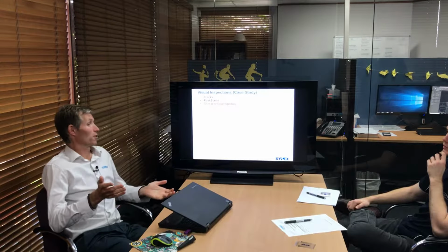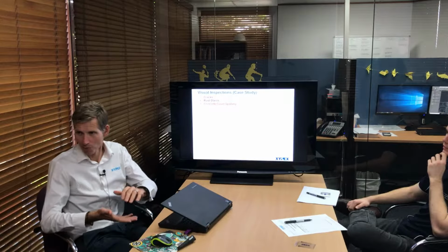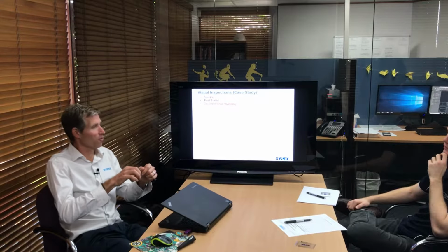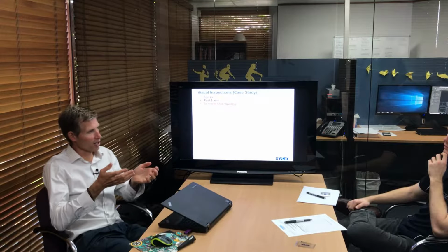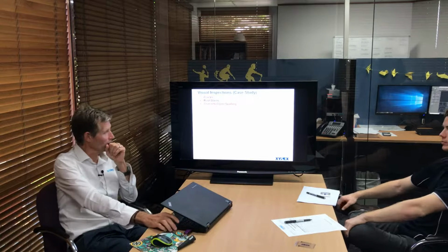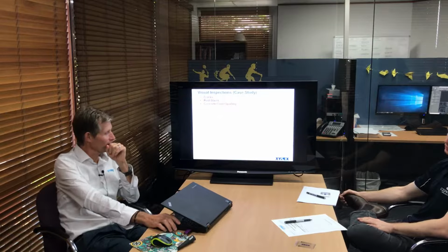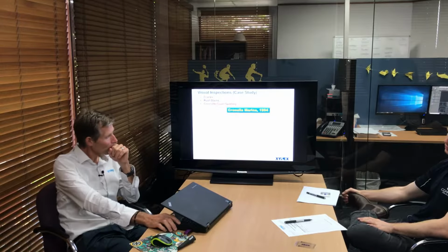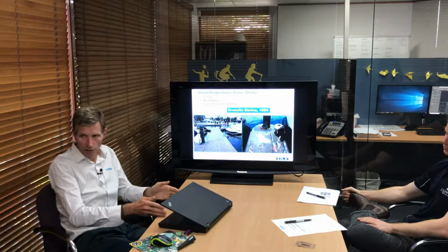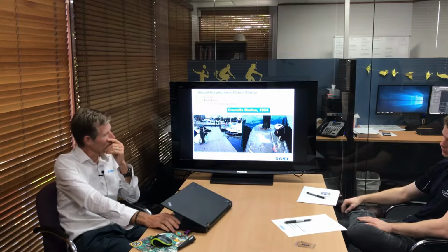Normally what that tends to mean is that on the surface the concrete appears to be in good condition, but as we know, it's really what's happening below the surface, and more importantly how the rebar is tracking, that determines how you can predict the residual service life of a concrete structure. So this led to doing a bit more investigative work. They've done some destructive testing and taken some core samples from both structures.